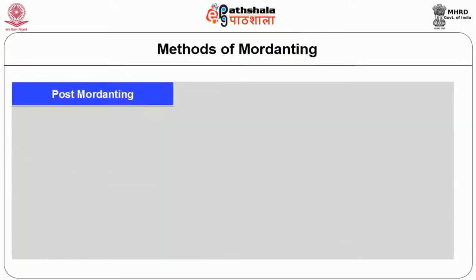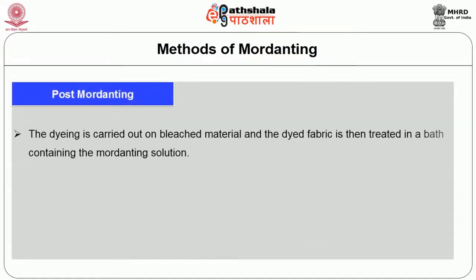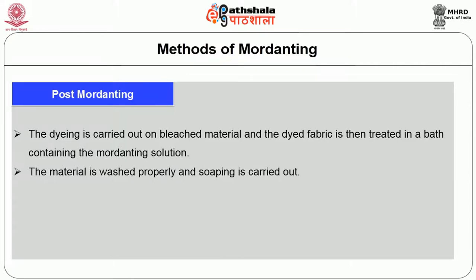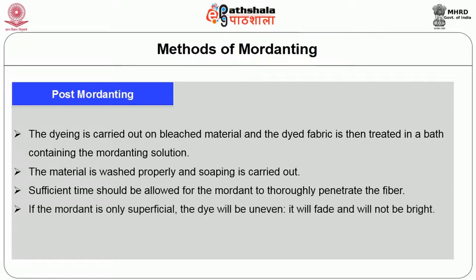In the post-mordanting method, dyeing is carried out on bleached material and the dyed fabric is then treated in a bath containing the mordanting solution. The material is washed properly and soaping is carried out. Sufficient time should be allowed for the mordant to thoroughly penetrate the fibre. If the mordant is only superficial, the dye will be uneven, it will fade and will not be bright.